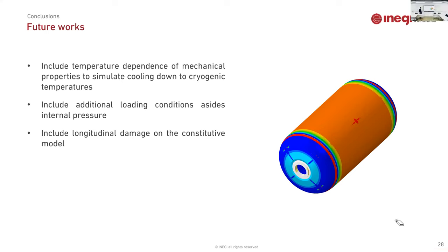I already have, in the last months, done some additional work. What is intended is to perform the same dynamic mechanical analysis test, but instead of looking only at room temperature, let's say 20 degrees to 100 degrees, I want to see 100 degrees to minus 200 degrees, for example. So the complete temperature range. What is interesting is that, for example, the elastic modulus of the resin increases almost 3 times, okay? The resin at room temperature is about 2,000 megapascals, and it goes almost to 6,000 megapascals. This is why we need to consider the temperature dependence.